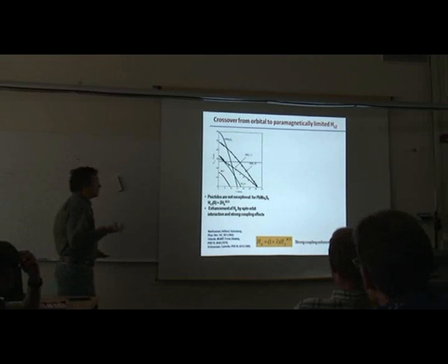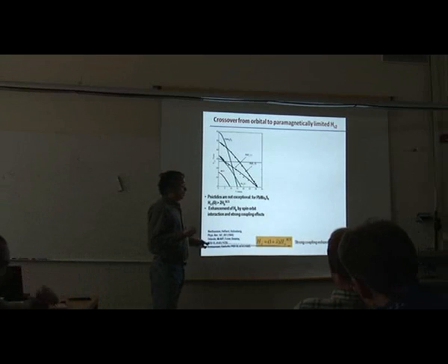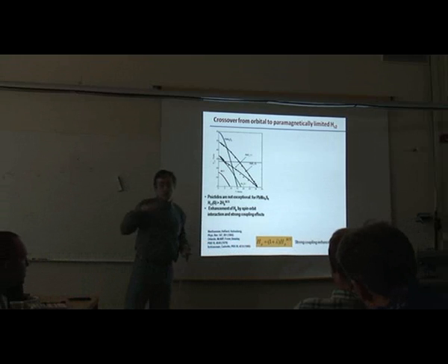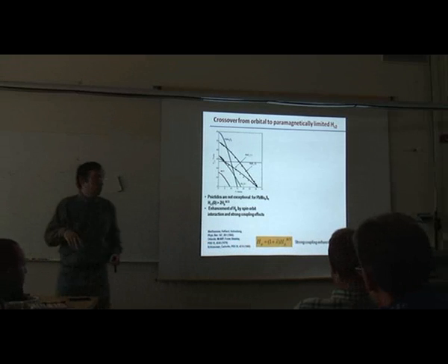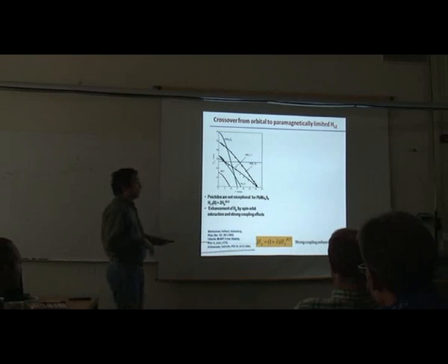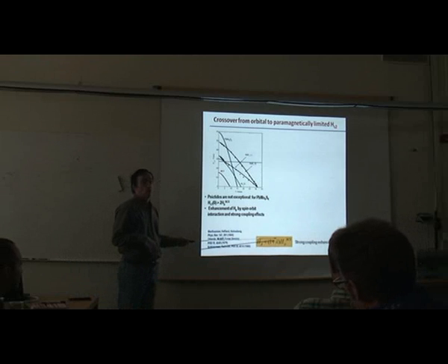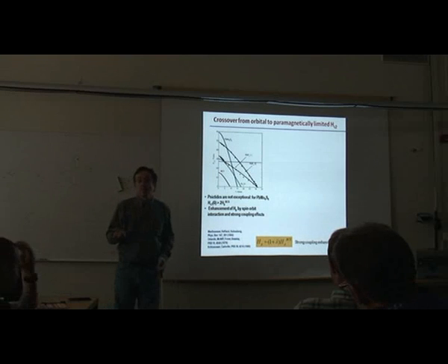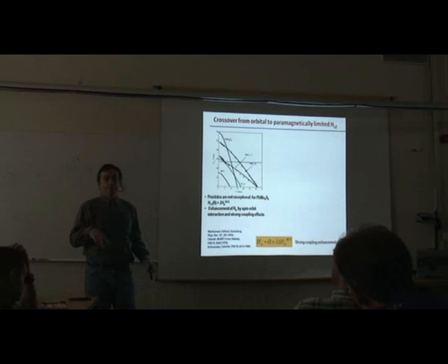And usually people understand it either by taking into account spin-orbit effects or simply by taking into account strong coupling. In Eliashberg theory, the paramagnetic limit is enhanced by a factor of 1 plus lambda. Lambda is the electron-phonon coupling constant. So is the g factor important for this?